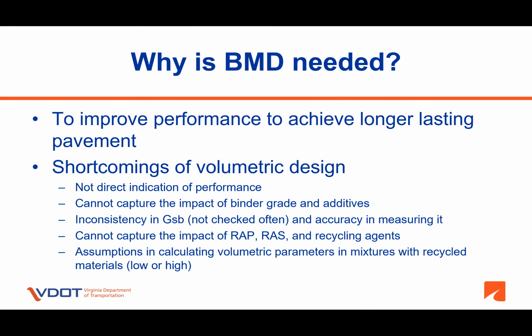Why is BMD needed? The answer to this question is simple. We need BMD to improve performance of asphalt mixtures so that we achieve longer lasting pavement. The current design, SuperPave design, initially had a tiered approach that included performance testing. However, because of the concerns associated with the routine use of performance tests, such as complexity and time needed to run the tests, as well as the cost of equipment, the design parts of the SuperPave that included performance testing are largely abandoned. Today, what we have is the volumetric design part of the SuperPave methodology, and the volumetric design